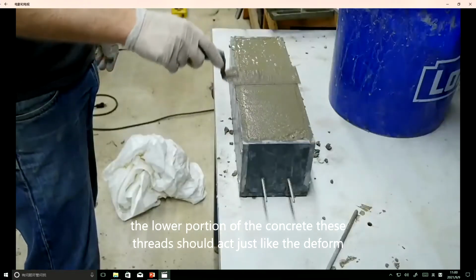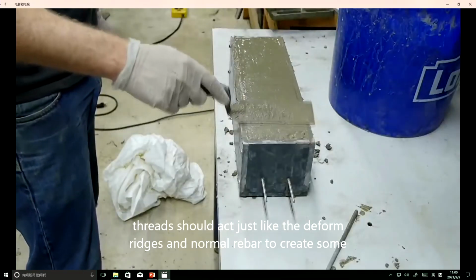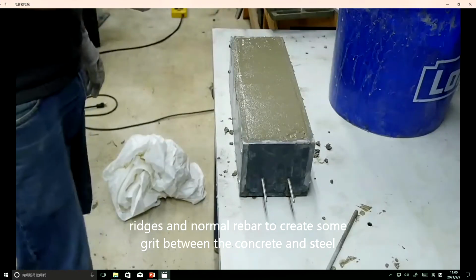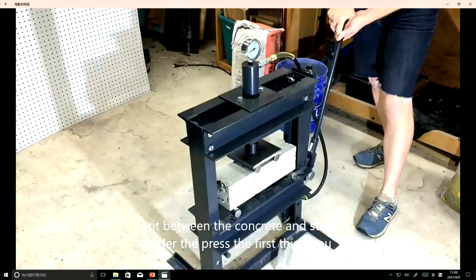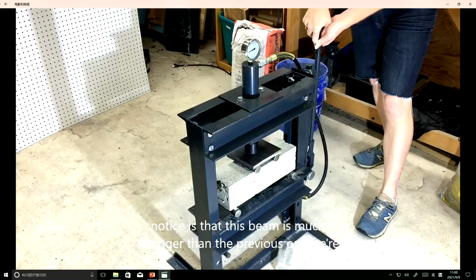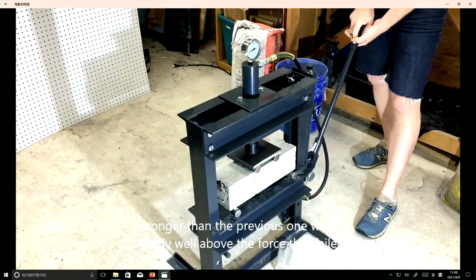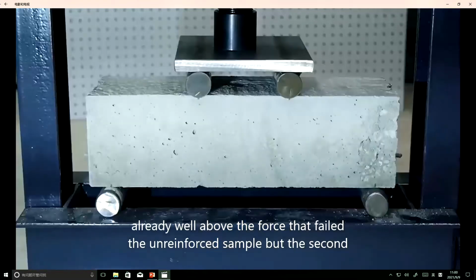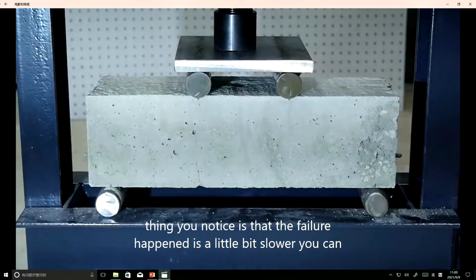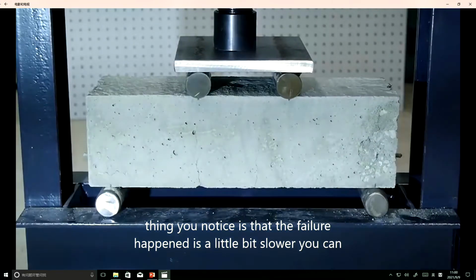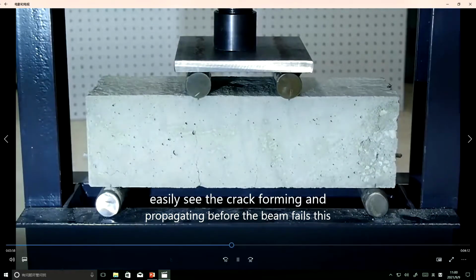These threads should act just like the deformed ridges in normal rebar to create some grip between the concrete and steel. Under the press, the first thing you notice is that this beam is much stronger than the previous one. We're already well above the force that failed the unreinforced sample. But the second thing you notice is that the failure happens a little bit slower. You can easily see the crack forming and propagating.